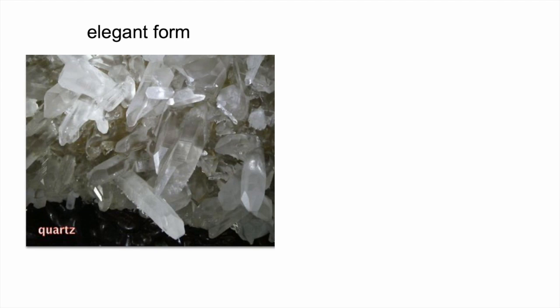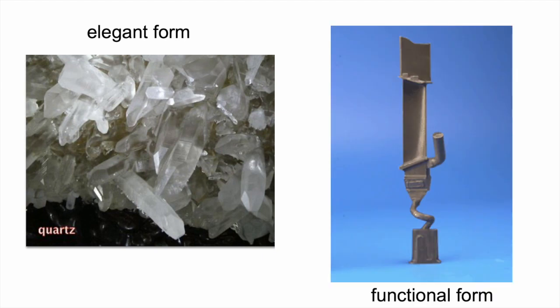We can make crystals which have an engineering function. This, for example, is a single crystal turbine blade found in all aircraft engines. These single crystal turbine blades serve in the hottest part of the aircraft engine — an environment of about 1500 degrees centigrade, which is greater than the melting point of the nickel-based superalloy material. The way you make this single crystal — which has an aerodynamic shape — is you solidify directionally starting from the bottom and going upwards. Many crystals nucleate and grow, the one that grows fastest makes it through the spiral, and the rest solidifies as a single crystal.